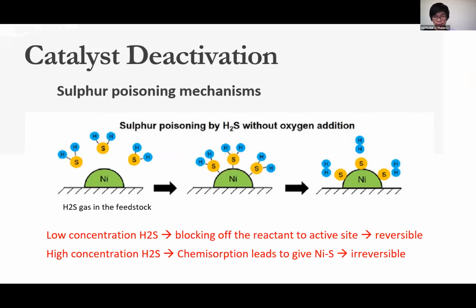Catalyst deactivation: the direct interaction between sulfur from the hydrogen sulfide in the feedstock and the nickel catalyst active site. The actual deactivation mechanism depends on the hydrogen sulfide concentration. At low concentration, the catalysts are deactivated via sulfur physisorbed on the catalyst surface, thereby blocking access of the reactant to the active nickel site. At higher concentration, the chemical potential of sulfur increases. This favors the chemisorption of sulfur into the nickel-based catalyst, leading to the subsequent sulfidation reaction to give nickel sulfide on the catalyst surface.